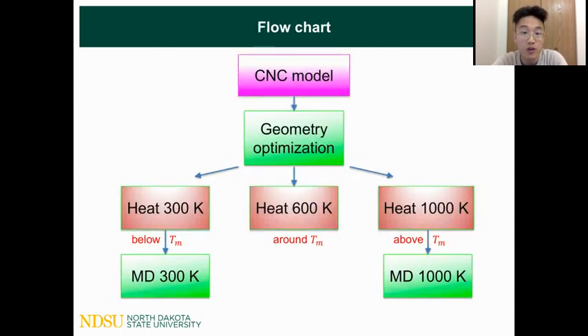And then we do the geometry optimization first to make sure the whole system reaches the local energy minimum state. And then the heat is applied from 300 K to 1000 K. For cellulose nanocrystal, the melting temperature is around 600. So we choose three typical temperatures: well below the melting temperature, approaching, and even well above the melting temperature. So the goal of this project is to have a molecular level understanding of how the applied heat will influence the conductive properties of cellulose nanocrystal. At the same time, we also look at the molecular dynamics at 300 K and even high temperature. Next, please.